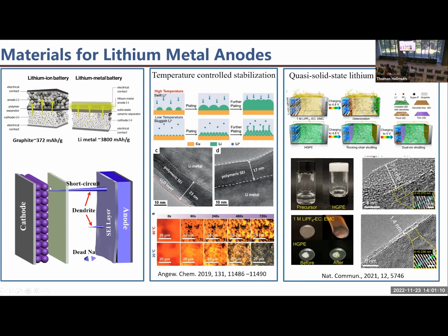But one of the key issues with metal anode is the dendrite formation, and the dendrites actually pierce the separator and cause short circuiting. The batteries don't really work very well. Our group reported many articles, but I chose 2 articles to show here.